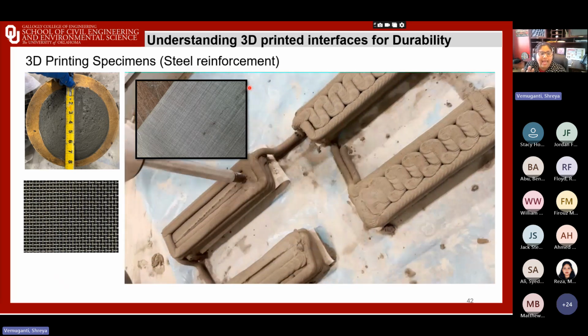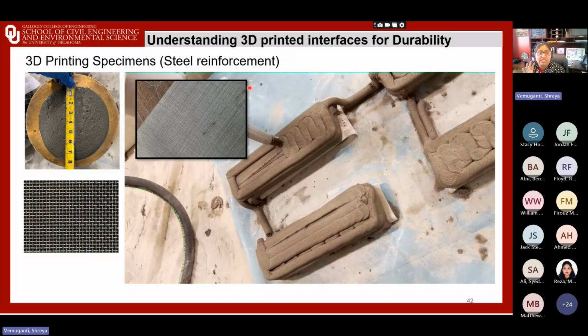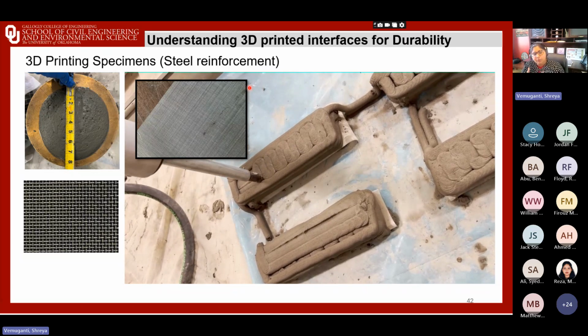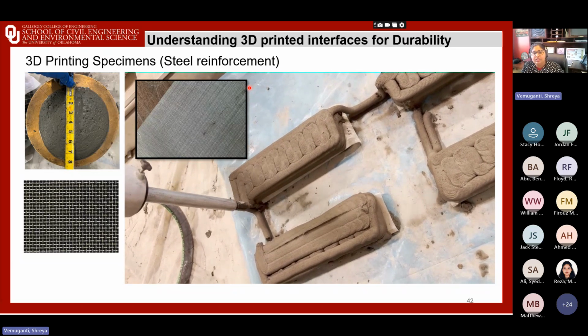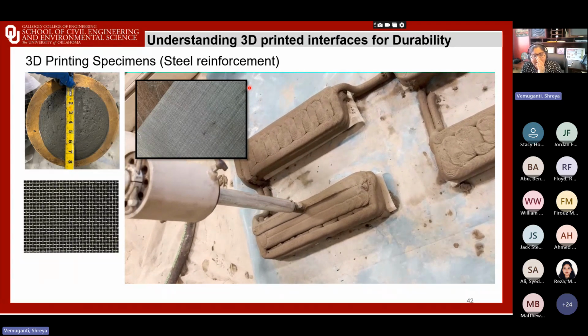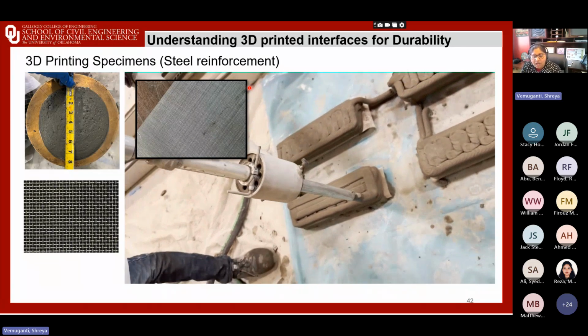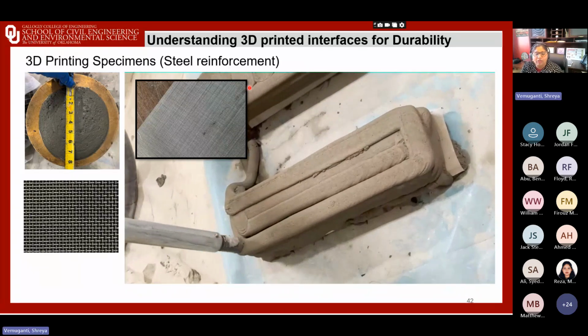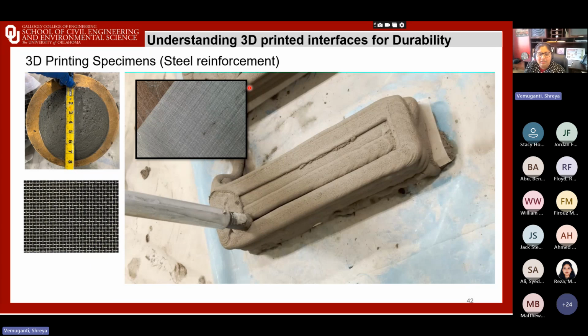This particular one is the last one of our interface reinforcements, which is the steel reinforcement. It's important to understand steel reinforcement related performance as well in these aggressive environments because it sort of gives us a benchmark. It's FRP versus steel, not necessarily, but we are trying to also understand how maybe this grid size could affect also. If you see steel, this is such a stiff mesh that we obtained, right? So during compaction, there's not any stretching or there's no effect of the nozzle compaction on the steel itself. So it's already very stiff and provides great strength.